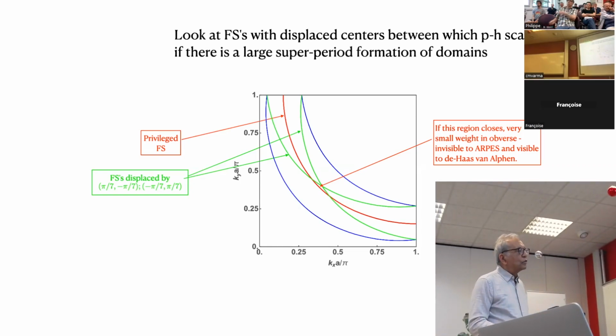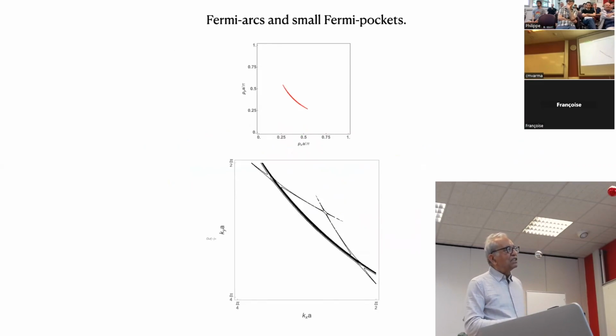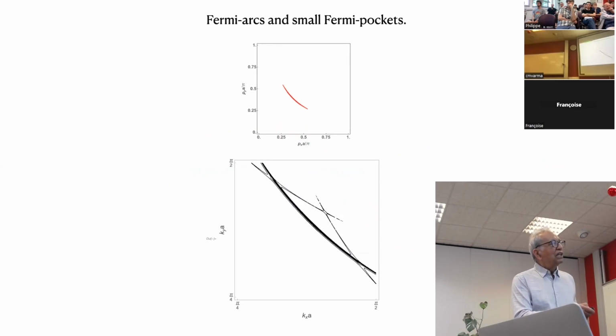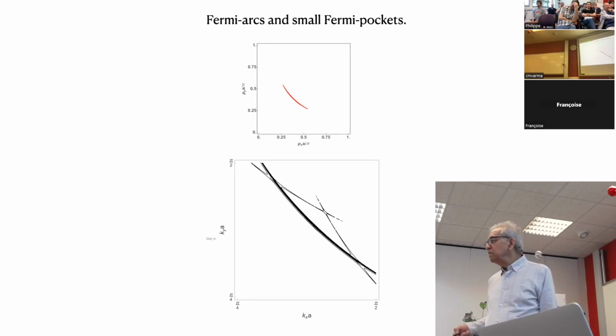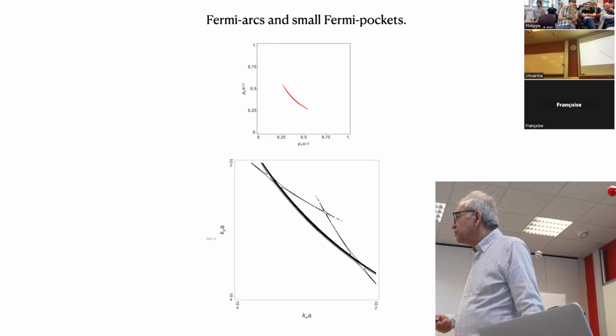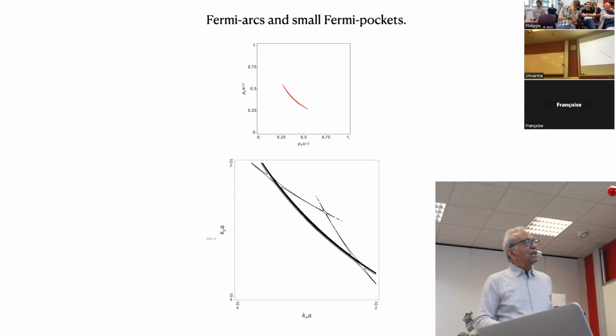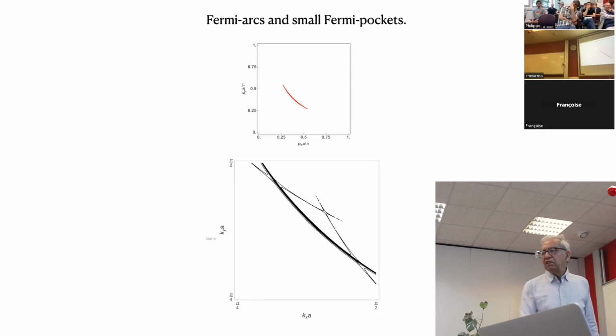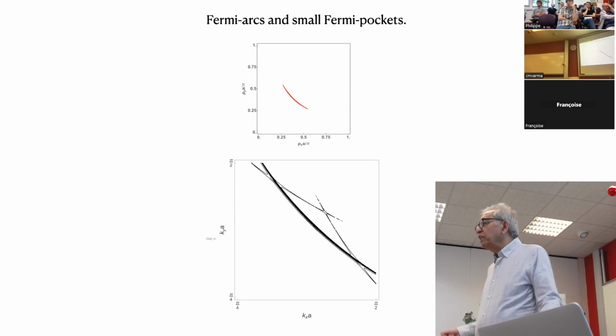Okay? And what we discover naturally is that this is done on Mathematica, and if you do Mathematica over the whole Brillouin zone and with not a bit of a poor resolution, you get a Fermi surface in this region, and there's all kinds of things happening here, but the intensity is falling off as 1 over the square of the number of domains. Okay? Now, if you look here, you see this is an absurd thing, right? You have a Fermi arc. If you look more carefully, you see that this was really coming from the intersection of those three things, and that these things on this side have very low intensity compared to this thing, and this forms a closed surface. So that's my resolution.